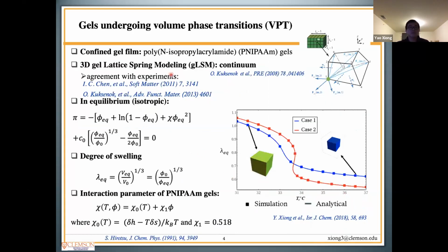The process of gels undergoing changes in their volumes in response to external stimuli is called a volume phase transition. In our research, we use PNIPAM hydrogel, which has a lower critical solution temperature around 33 degrees Celsius. We investigated the pattern formation in confined PNIPAM hydrogel by simulations on continuum scales. Our computational approach is 3D gel lattice spring modeling. In this approach, gels are discretized into elements.